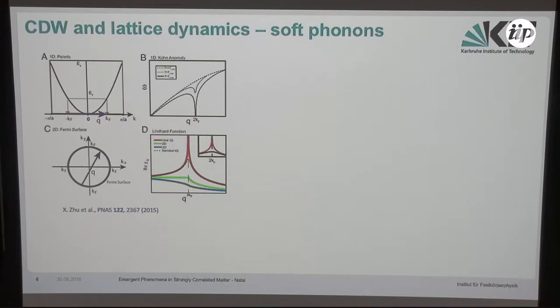So our approach to that was, okay, if we have a charge density wave in the cuprates, it must be interesting to look at the phonons. Because you know that in the original 1D case, the Peierls textbook calculation, a 1D system is going to be unstable to the formation of a charge density wave, and it manifests itself by a softening of the phonon at the nesting wave vector of the Fermi surface. But it strictly worked only in the 1D case. As you go to higher dimensions, the real part of the electronic susceptibility, which has a clear maximum and actually a divergence in 1D, is completely washed out.